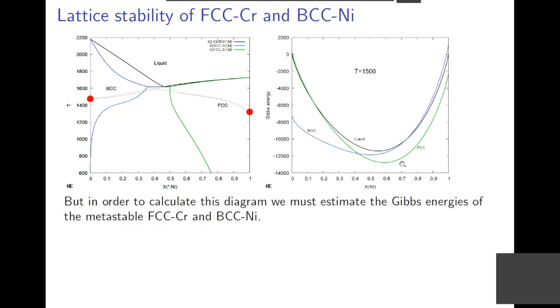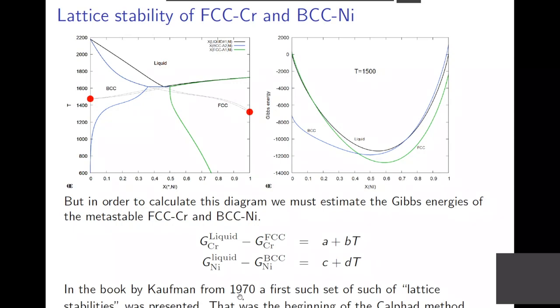And you have an FCC phase for nickel, which is stable on this side, but you need to predict in your modeling a value for the FCC chromium phase. And here you can see that at 1500, chromium FCC should actually be liquid. But of course, you can never obtain that in an experiment. So those lattice stabilities were established by Larry Kaufman in the 1970s. And they are just normally linear temperature-dependent functions. And those are related to an enthalpy of melting and an entropy of melting. And you can actually, in this case, estimate those values from the stable phase diagram.